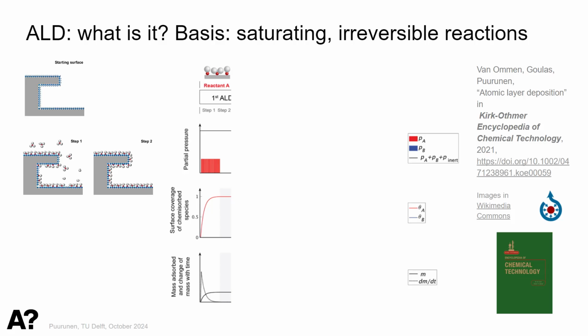So you bring in the first reactant through gas phase to the surface. It reacts, and it reacts until saturation has taken place. So the full surface is covered with adsorbed species, and whatever excess you have there is removed either by purge or evacuation. So then after this first reaction is completed, you have a well-defined surface. Here I have the process with time, so you just bring in the partial pressure of reactant A to the surface, and that's where adsorption happens. And so this would be the coverage, theta, coverage of chemisorbed species.